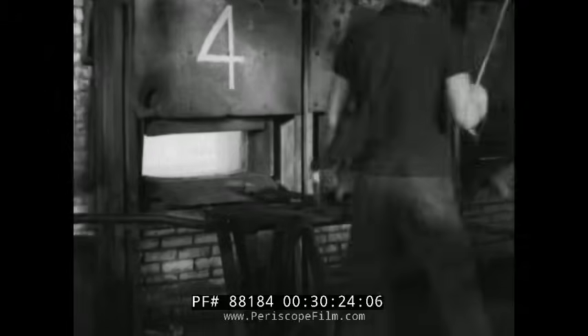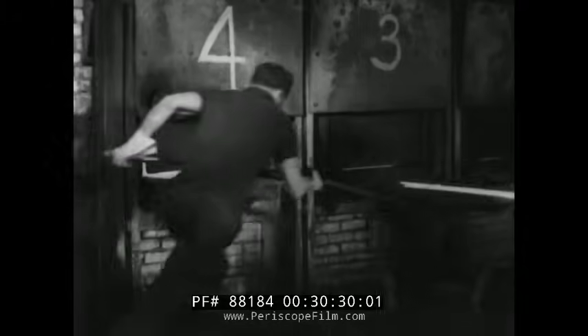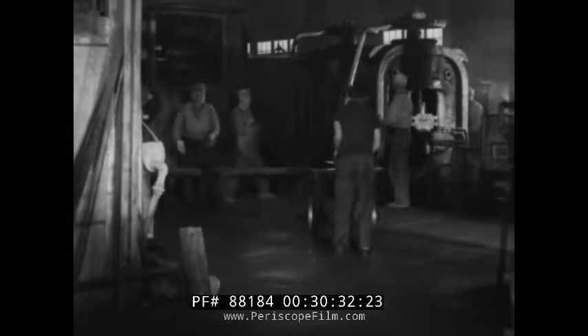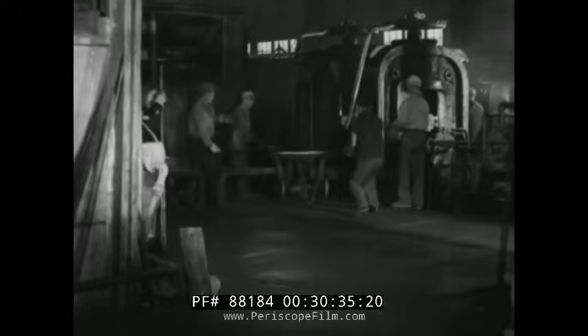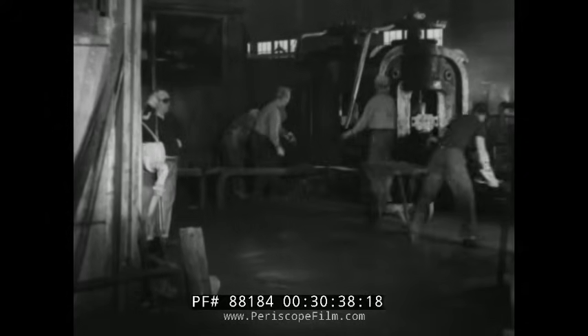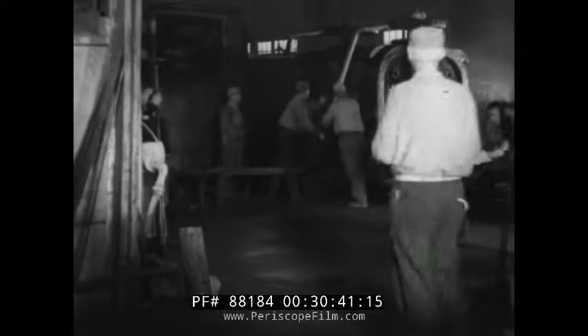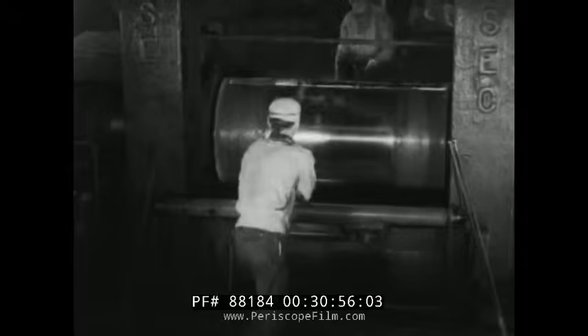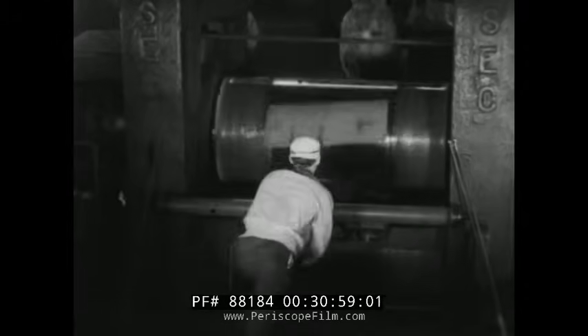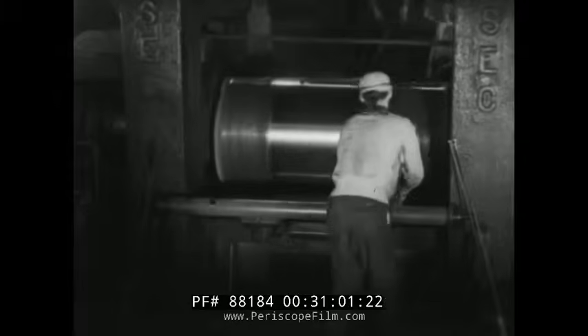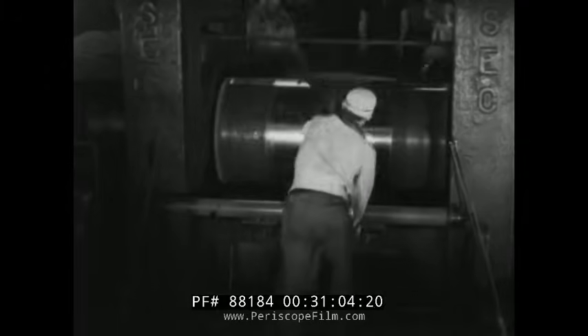Sheet bars are reheated under an extremely close control both as to temperature and atmosphere. When ready for hot rolling, a pair of bars are withdrawn from the furnace and rushed to the mill. The first operation is known as breaking down. The sheet bars are passed back and forth through the hot rolls until they begin to lose their heat. Then they are returned to the furnace. Following the second reheating, the bars are brought back to the mill for further hot rolling.